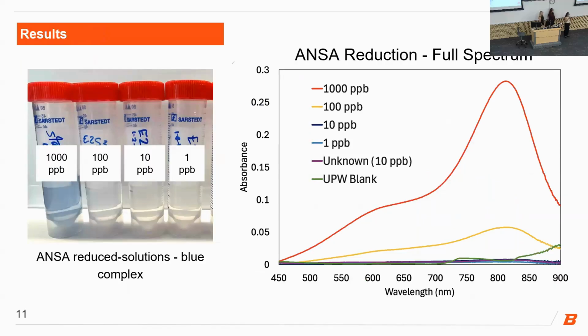So for our results, our first set of samples, we use ANSA as a reducing agent, and as we can see in the image over here, it turned blue. And when we look at the full spectrum, we see absorbance peaks for two of our highest concentrations at 850 nanometers. However, below that, we could not see any absorbance peaks, which means that our limit of detection could be between 10 and 100 ppb.